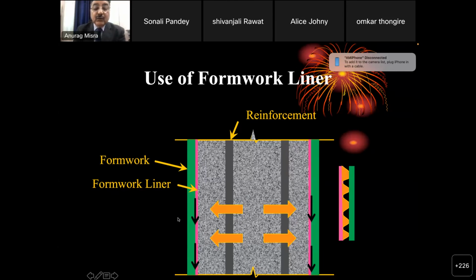So this liner, if used, is one of the mechanisms by which we can reduce the effective water cement ratio obtained here in the outer cover zone concrete. So what happens is that when you vibrate the concrete, the water tries to get accumulated here, and then it flows through this membrane and by gravity drains off. By this process, you can actually reduce the water cement ratio here, which results in better and compact cover zone concrete. So the effective water cement ratio in this zone becomes lesser than the core concrete, resulting in better compact cover zone concrete and better durability.